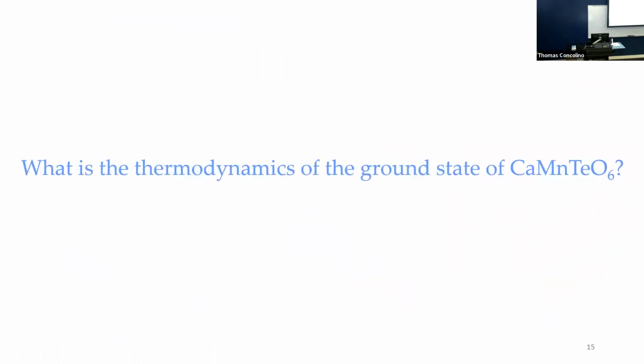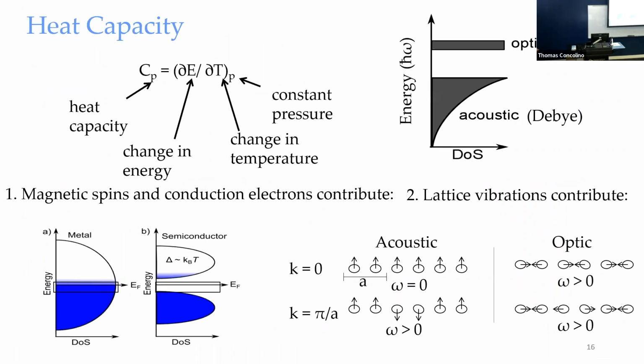So what is the thermodynamic of the ground state of the material? So we look into specific heat data, which is the change in energy with respect to change in temperature at constant pressure. So there are two main contributions to heat capacity. You have magnetism or conduction electrons, and phonons, which are lattice vibrations. We also want to look into the phonon contribution in terms of acoustic phonon and optic phonon, and we use the Debye-Einstein model in order to analyze the phonon contribution data.